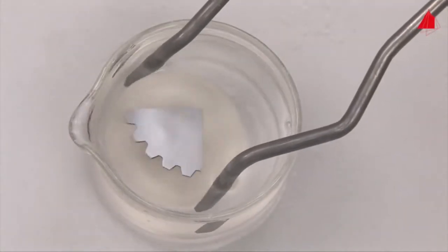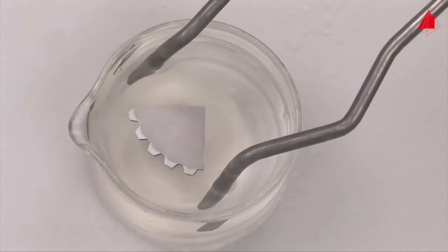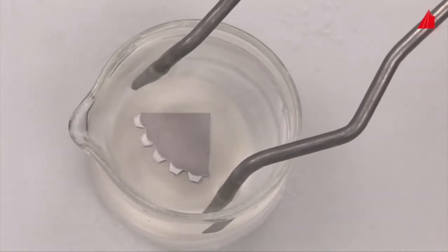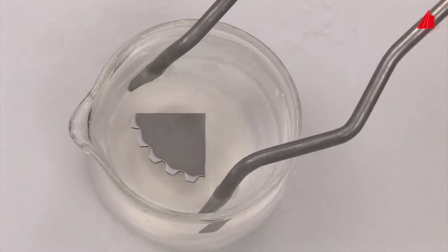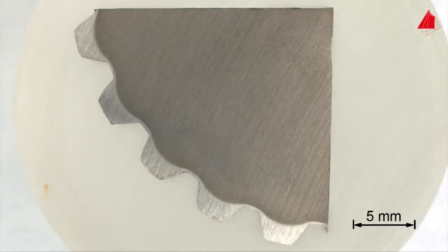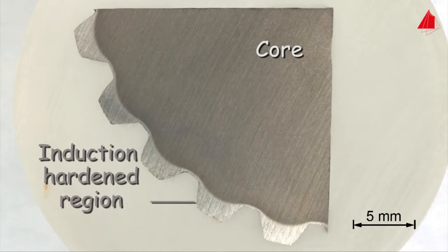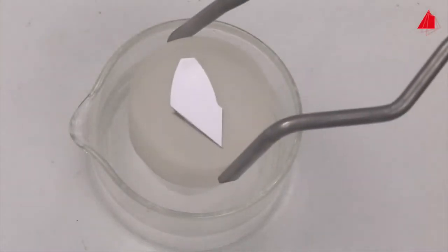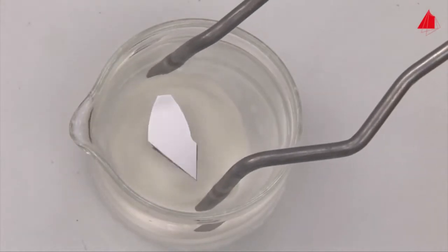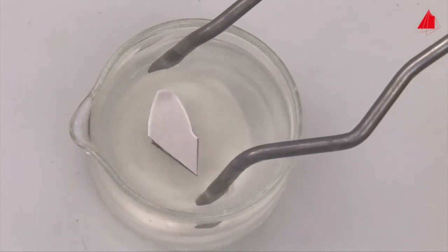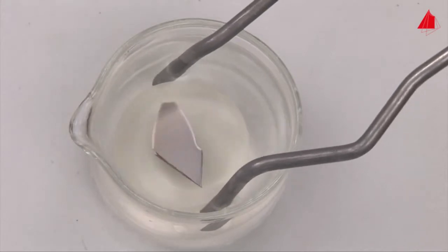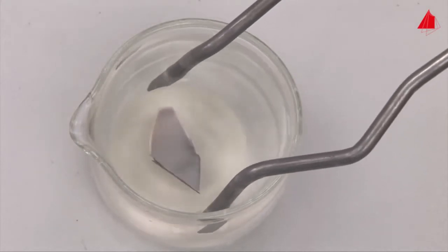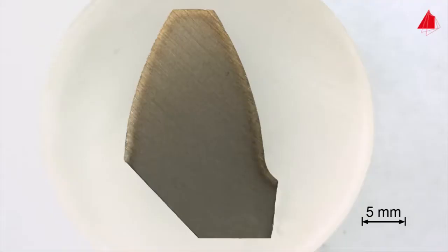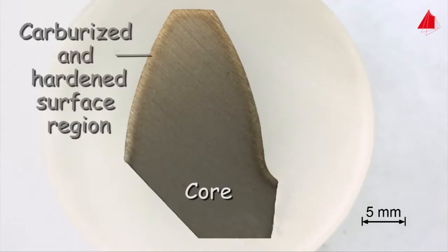This section of a splined shaft is induction-hardened as well. As a result of the etching process, the outline of the hardened surface layer may easily be recognized. The dark area represents the core that has not been hardened. This is a tooth from a case-hardened gear wheel. The surface region of the gear wheel has first been carburized at high temperature and then quenched. The etched sample shows the smooth transition from the carburized and hardened surface region to the softer interior.